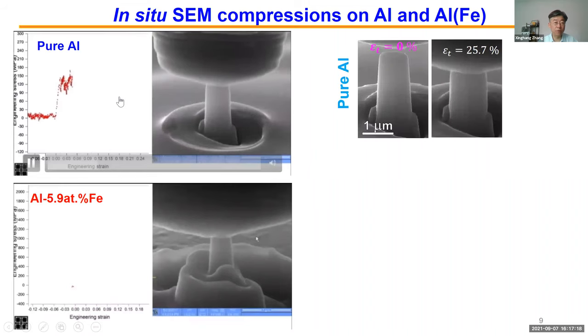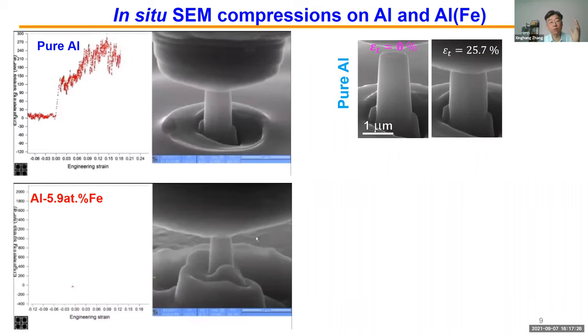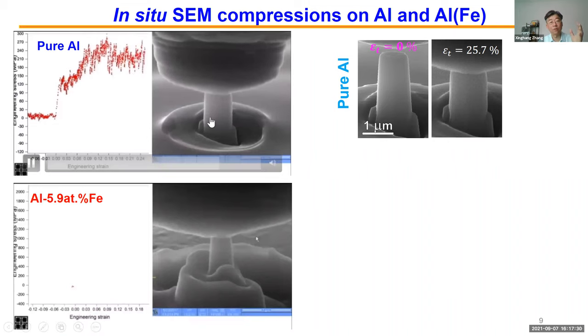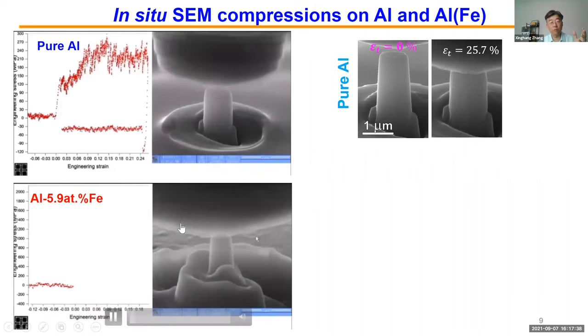And you see these very typical serrations because this is single-crystal-like aluminum. So you have a lot of load drops due to the initiation of dislocations on certain crystallographic planes. So it's pretty rough, noisy. And the flow stress is about 200 MPa, pretty soft. But if you do the same kind of measurement for aluminum, now doped with close to 6